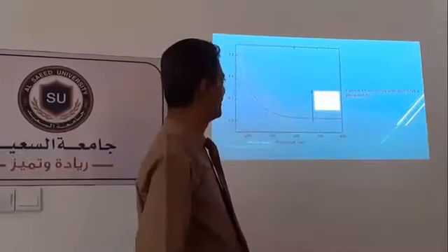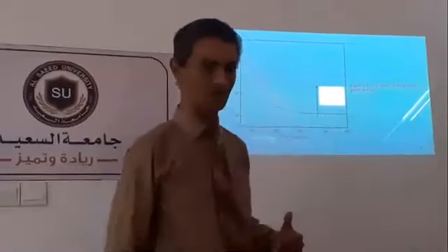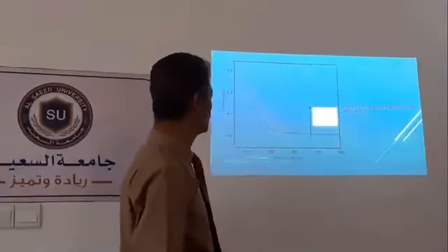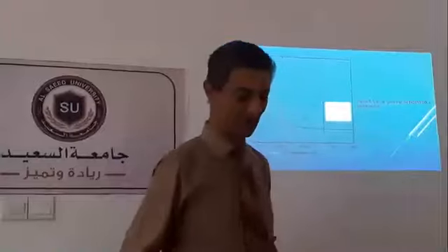Here we reported the UV-visible spectra of the BIMNVOX photocatalyst. We can see that as the manganese concentration increases, there is also a shift in the absorption edge to longer wavelengths, indicating a narrowing of the band gap with increasing doping concentration.